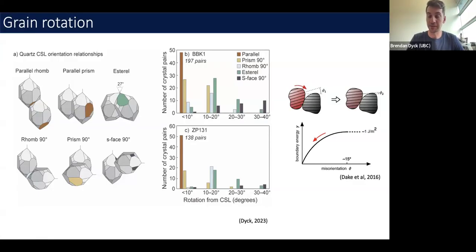Now this might be telling us something about how these quartz grains came together, because of the driving force for crystals that are close to each other. Maybe they're meeting on their rhomb faces, but they're meeting at, say, 45 degrees in terms of their c-axes. That's not a low energy orientation relationship, but if through stochastic processes they're able to be moved and realigned into a low energy relationship, then the grain boundary energy of that segment is going to drop.